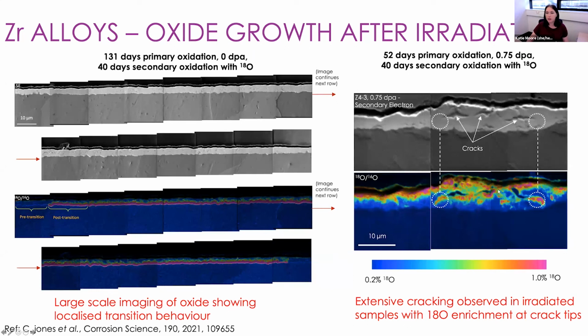But you can see that this zirconium alloy oxide is rather cracked because of this irradiation. And we can clearly see that water has penetrated down through those cracks, and it started to grow new oxide here using that oxygen-18 labeled water. We've got the cracks starting to penetrate down to the metal oxide interface. We can also see some very small regions here where the oxygen is able to penetrate through the oxide. It's starting to break down. So we get extensive cracking once we've irradiated the sample.